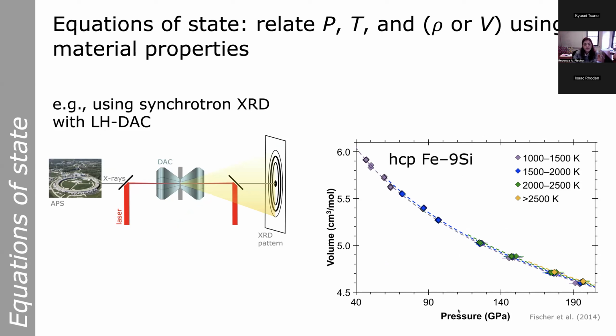This is a thermodynamic framework that lets us relate pressure, temperature, and density, or equivalently molar volume, using material properties. And there's a number of ways you can determine the equation of state of something using different experimental or computational techniques. In this example, we used synchrotron X-ray diffraction with a laser-heated diamond anvil cell. So we had a tiny sample pressed between two diamonds to generate high pressures, used infrared lasers to heat it up, and while it was at those high pressures and temperatures, we did X-ray diffraction. From those diffraction patterns, we could determine its density at all these different pressures and temperatures. So this is an example of what this looks like.